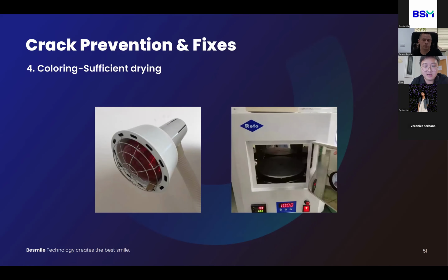We can use this light or this kind of oven to dry the restoration. If you use a light, we recommend the distance between the restoration and the light is 90 millimeters. If you use the oven, we recommend you to set the temperature from 90 degrees to 100 degrees. And for the single unit and small bridges, the drying time is like half an hour, 30 minutes. And the bigger the restoration, the longer the drying time. So for the full arch, we recommend the drying time is more than 60 minutes.